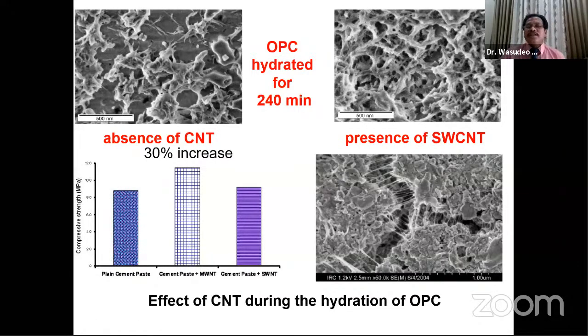And also there are three types of material: the plain cement has this type of morphology, and the cement with the single walled is shown here, this type of nature. And here you can see why this material increases the strength: the cement mixed with the multi-wall. The nature is shown here. As compared to this, it is very compact, and because of that it gives more strength, and it is also durable. So hydration can take place in this process by mixing multi-wall carbon nanotubes. So it becomes stronger and tough.